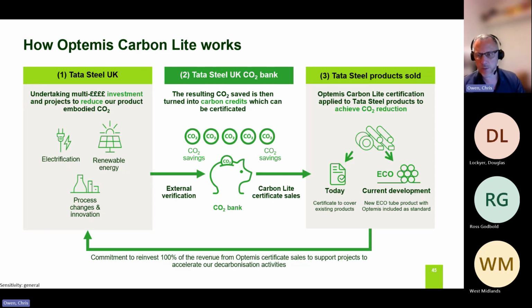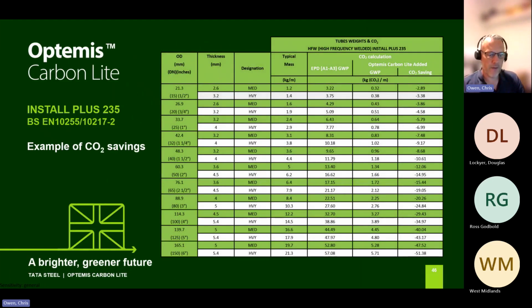And rather than us saying that we've got a small percentage reduction in embodied CO2 across our products, we're focusing on key products such as our building services tube and applying all those carbon credits, which allows us to reduce the embodied carbon by up to 90%. So we can see from this table here that if we start looking at the weight of a medium tube or a heavy wall tube, then having a higher grade of steel, such as the 235 grade compared to the standard, which asks for a 195, means that you can go to a thinner wall, still get your pressure integrity, but you've got a weight saving, which is a CO2 saving as well. However, applying the Optemis on top of that, we can bring it down by up to 90%.